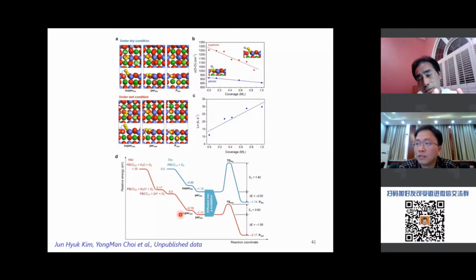Because as soon as you operate your cell, oxidation of hydrogen produces water. And if you have a catalyst there that captures that water as it is produced, and uses that water to do reforming, then at the active site for the electrochemical reaction, your steam to carbon ratio is always high. So that will prevent coking. I think that's one of the most effective strategies. You need to locally increase the steam to carbon ratio.